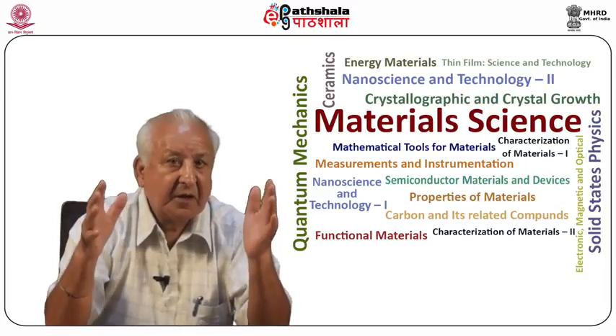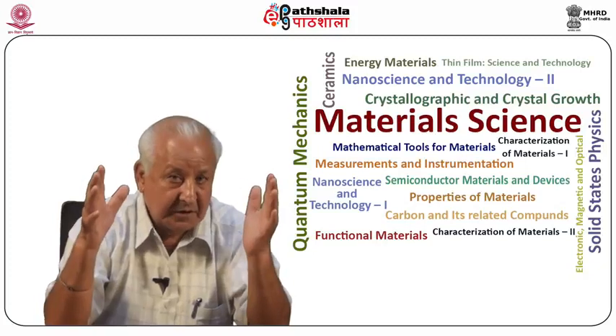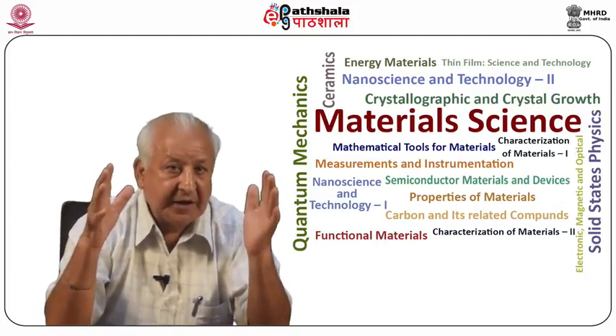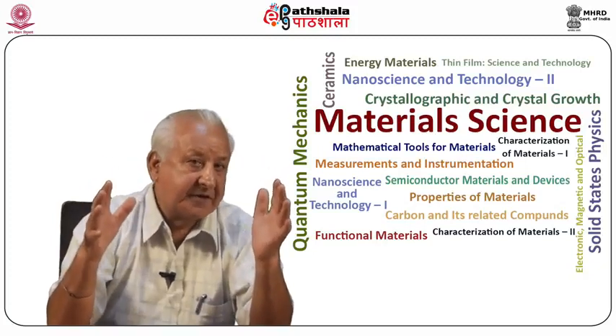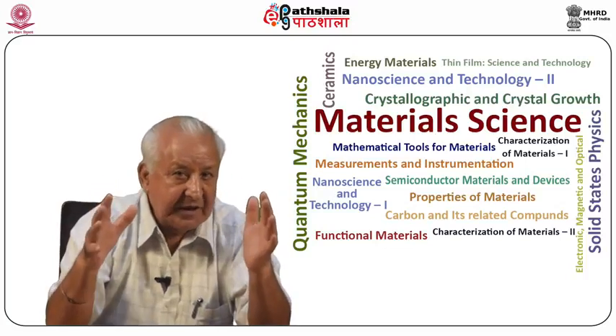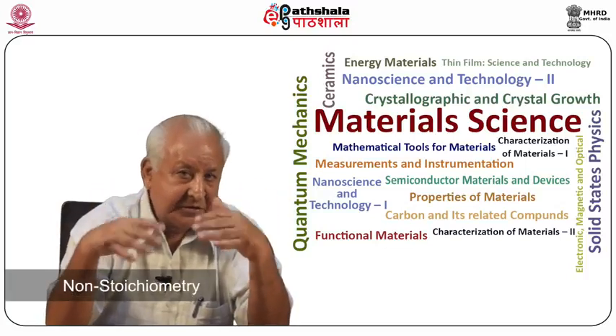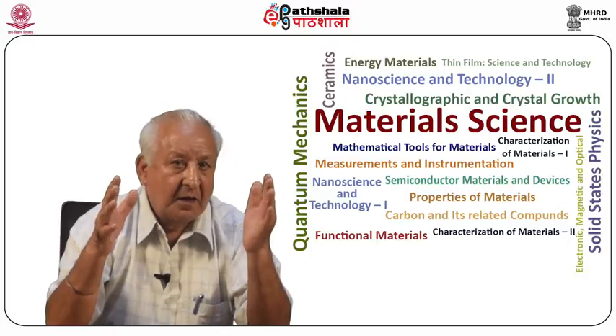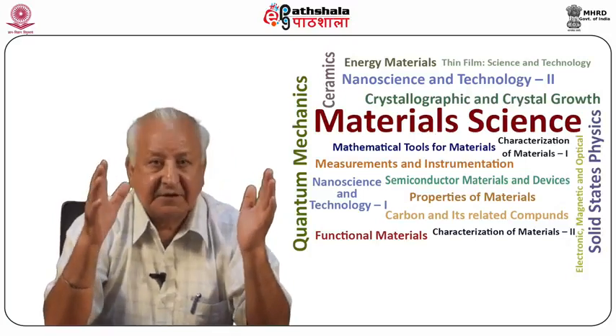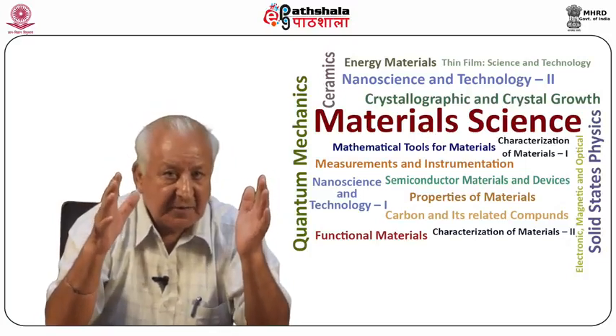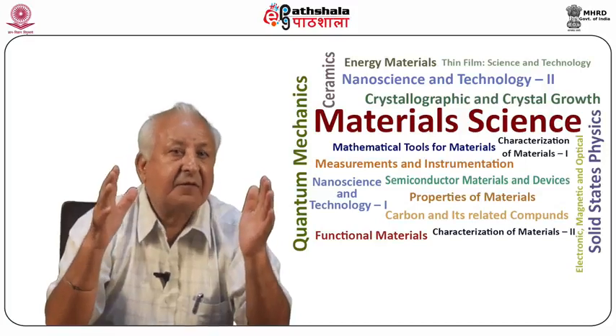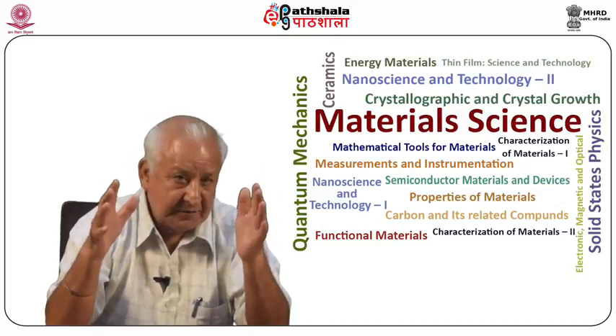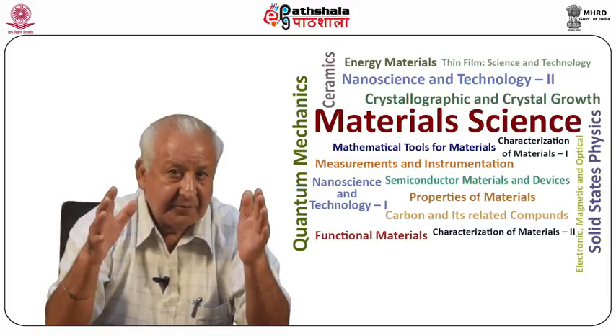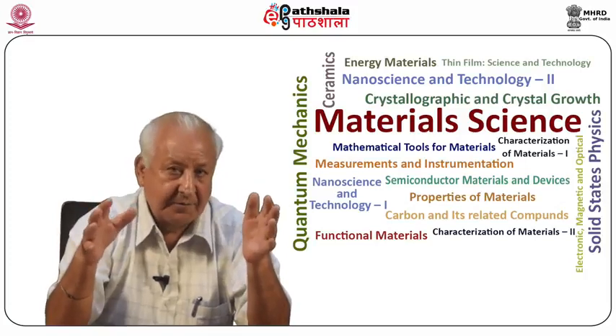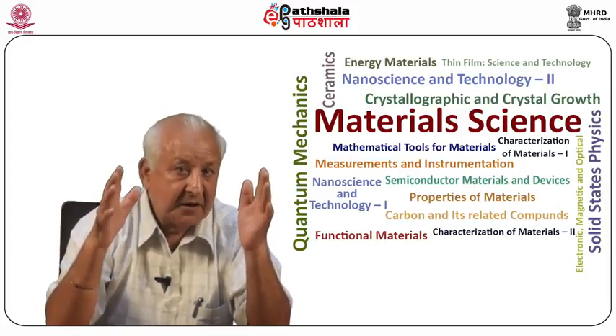It results in coloring of the crystal due to creation of F centers associated with non-stoichiometry. The density of F centers depends upon the density of potassium atoms in the vapor and therefore the temperature T2.